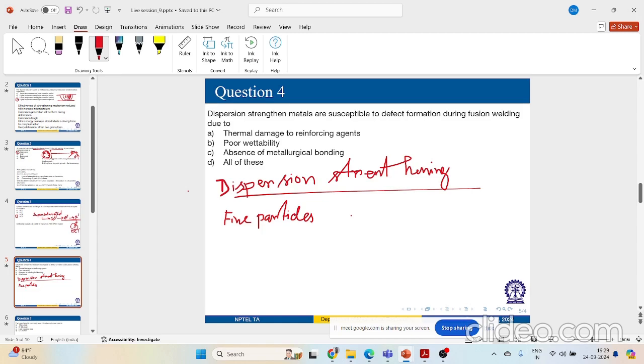Now, common materials that can be dispersion strengthened. That can include aluminum, titanium, and some steel materials, like stainless steel, can also be dispersion hardened. So people have made these metal matrix composites, and these particles you call dispersoids. So Al2O3, aluminum oxide, can be a particle, silicon carbide a particle. Mostly oxides and carbides are used as this distribution of particles, right?